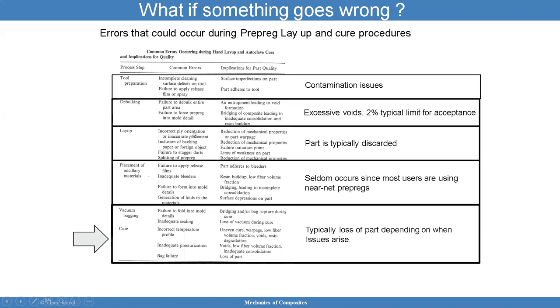Layup: an incorrect ply angle can be a problem. I'll bring that up later. That'll give very bad results. Say I want a ply angle of 0, 15, 40, but now I have 90, 90, 90. That's completely wrong, so the part needs to be completely discarded.